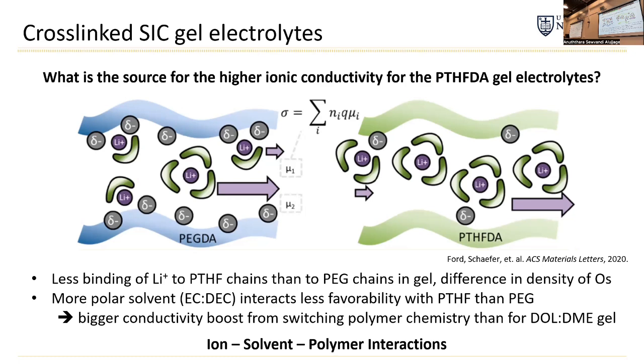But if it flows by and it's close to one of the PEG chains, we think the PEG chains are sticky, right? And so part of the lithium solvation shell may exchange for the polymer chain, and the polymer is not moving nearly as quickly as the solvent. So it's kind of temporarily stuck. The polymer chain is wiggling back and forth, but the lithium's kind of stuck there. And then only if it exchanges out to a total solvation shell is it able to move vehicularly, which is much faster. Whereas in the case of poly-THF, it's much less sticky. So there's fewer oxygens and there's more carbon and hydrogens, and so you have a much higher fraction of the lithium that has a full solvent solvation shell.